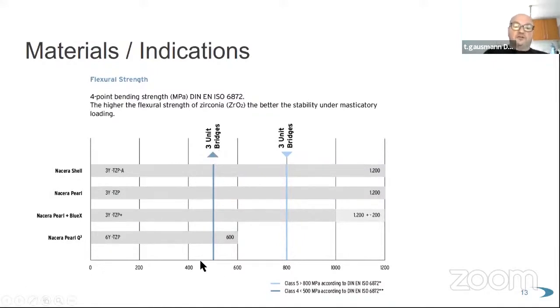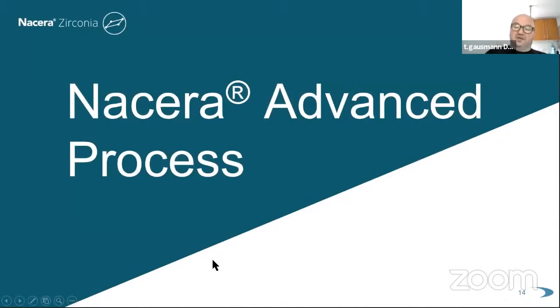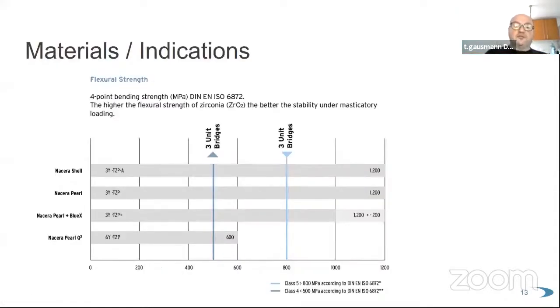You need a minimum of 500 megapascal to make 3-unit bridges. Minimum 500 megapascal. So cubics got 600, sometimes 650, depending on the measurement. I told you before, 3-point or 4-point or biaxial pressure measurement. It depends. Then you've got class 5 in dental materials in norm 6872. And this line here is at 800 megapascal. The minimum requirement for larger bridges is 800 megapascal according to this norm.